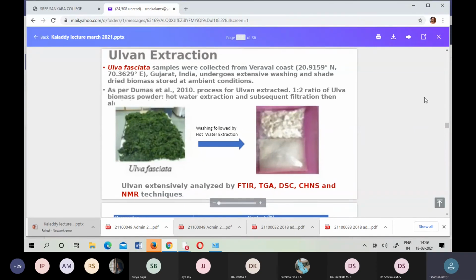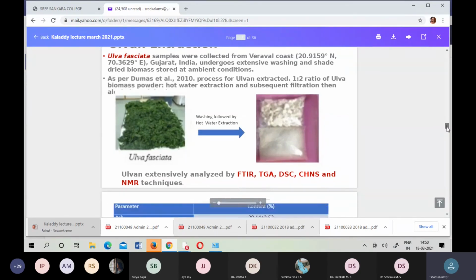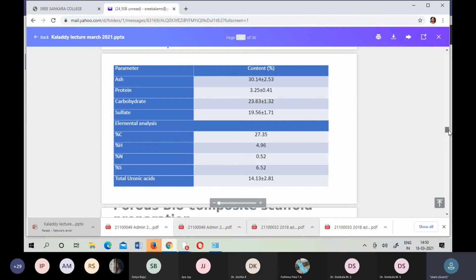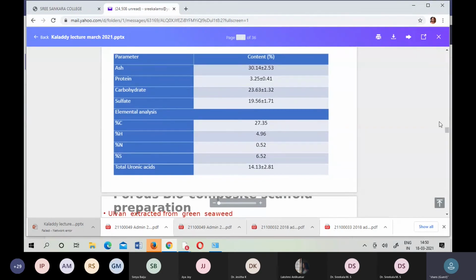We did all the analysis to confirm the quality, physical and chemical properties. Like I mentioned, the uronic acid moiety is close to 14%. This is something really different compared to others. And the sulfur quantity, from CHNS analysis, we are getting close to 7. And from the TGA, we know the species has close to 30% of ash content, and protein, carbohydrate, and other things are normal. So this is the chemical composition of Ulvan we are extracting from this seaweed.